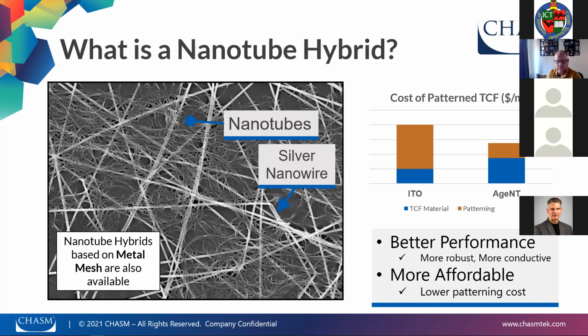Increasing conductivity in this case could mean either adding more silver nanowires or increasing their diameter, which then lowers the VLT or increases the haze of the material. So you put more silver down, it gets more conductive, but it also becomes less transparent. So the nanotube hybrid overcomes this traditional trade-off between transparency and conductivity, and I'll explain to you how.